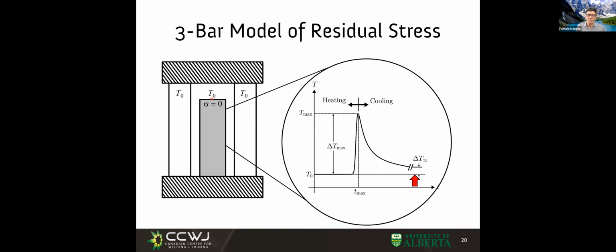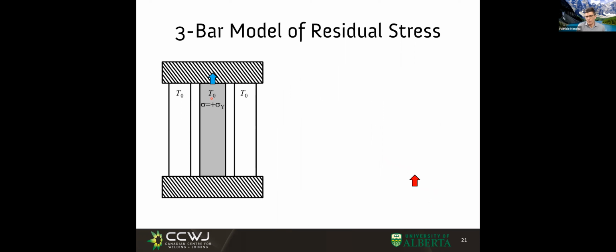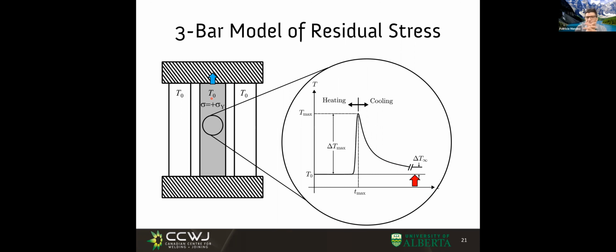But in reality, everything is attached. So what do we have? We need to have a tensile stress to bring it back to its original size. This is the origin of the final residual stresses as being tensile near the weld. It's because it plastically got smushed during the heating cycle, and then in the cooling cycle, it wants to cool down, but it just happens that it's too short. And that's why it ends up in tension.